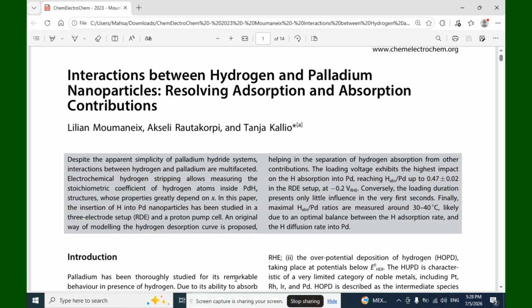Electrochemical hydrogen stripping allows measuring the stoichiometric coefficients of hydrogen atoms inside palladium hydride (PdHx) structures, whose properties greatly depend on X. In this paper, the insertion of hydrogen into palladium nanoparticles has been studied in a three-electrode setup (RDE) and a proton pump cell. An original way of modeling the hydrogen desorption curve is proposed, helping in the separation of hydrogen absorption from other